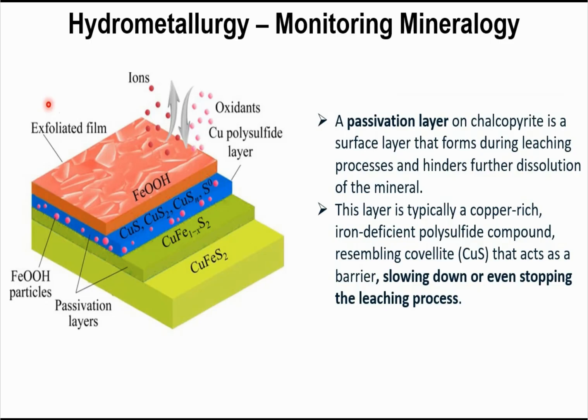And then the thing that's most hot off the presses for us is we've now figured out how to use the metal isotope composition of pregnant leach solutions to identify the formation of passivation layers. So the schematic on the left, the bottom is chalcopyrite. What happens during leaching is chalcopyrite will react with ferrous and ferric iron in the lixiviant. That drives oxidation of the copper iron sulfide or copper sulfide, which causes copper as a 1+ cation in the sulfide to be transported as a 2+ cation in the pregnant leach solution. Passivation layers commonly form and essentially create a shield around copper sulfide minerals in the heap that decreases the overall recovery of copper from the heap leaching operation.